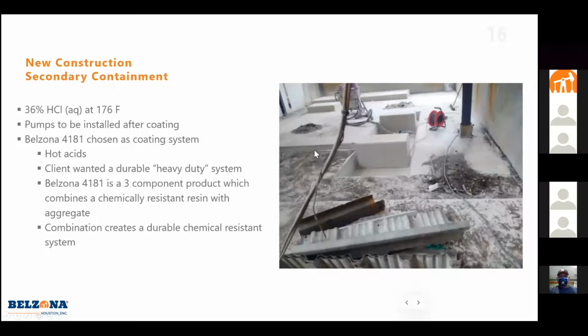Then finally, some case histories. We do anything from containments that have been there for years to new construction. So this right here is a new construction, 36% HCl at 176 F. So we have a hot acid. So for that reason, Belzona 4181 was chosen as the full system. Now, if you do remember, this was part of the rebuild section, but this coating can also be used to just coat everything. So it's kind of killing two birds with one stone. You're rebuilding and coating at the same time.